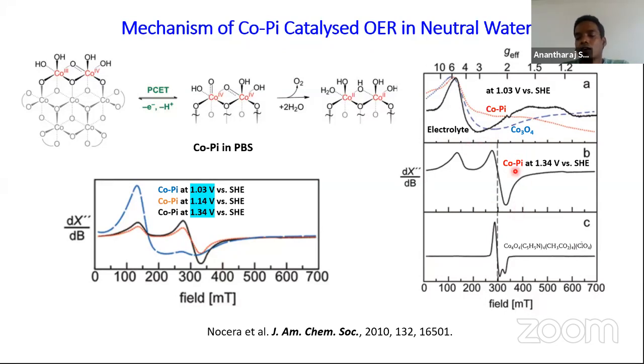So this gives a characteristic peak for a single unpaired electron, which is closer to the g factor of 2. So this indicated to them that there was formation of cobalt 4 plus. And to confirm that, they chose this particular cubane, where all the cobalt present is in the 4 plus state, and it also gave a similar EPR spectrum. And this was their solid proof for the mechanism they proposed, and they actually confirmed it. And they also did a potential dependent study for the same catalyst, cobalt phosphate. You can see at 1.3, you don't see any peak around this area.